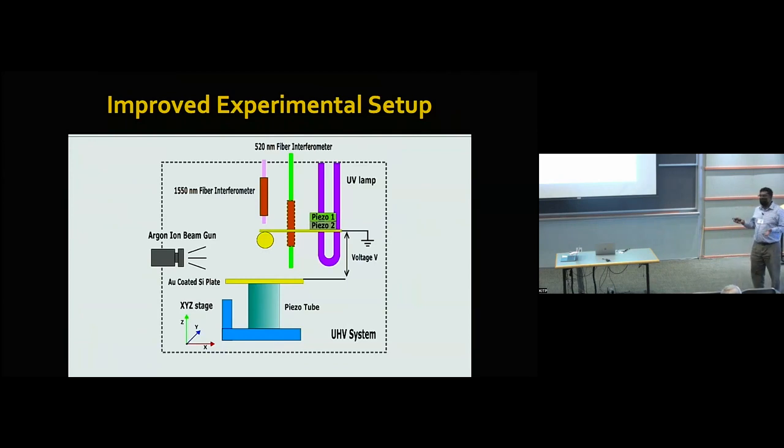if you do surface physics, which you do in ultra-high vacuum, 10 to the minus 10 torr, you usually bake the chamber to get rid of all the impurities in the chamber. We can't do that here because we've got a cantilever and thin coatings on the material. So the cantilever will, as people who do thermal physics know, completely curl up. So we can't do that, so we had to come up with this other way of doing it: use an argon ion beam to clean the surfaces, and a UV beam to clean the chamber. Okay, two things we had to introduce.